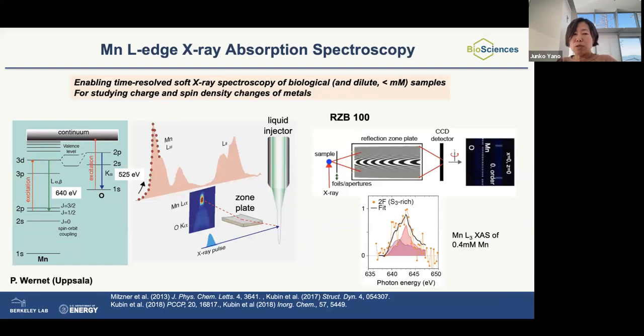And we also want to do manganese L-edge absorption spectroscopy. For that, of course, we need to go to soft X-ray energy. That means we need to do the experiment under vacuum conditions. We cannot use the tape drive, so we are using a liquid injector for that. For the L-edge, the challenge is that manganese fluorescence is around 640 electron volts, but oxygen K alpha is 525 electron volts. The oxygen concentration in an enzyme is about 50 molar, but manganese concentration is less than 1 millimolar. So how to live with this kind of huge background is a challenge.